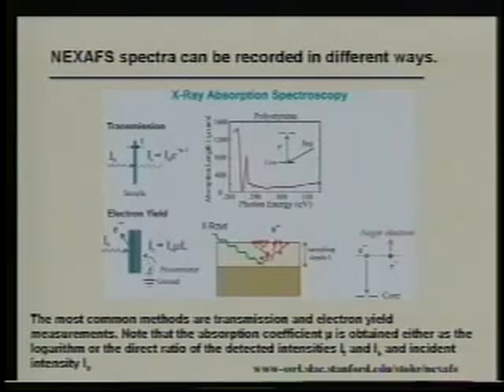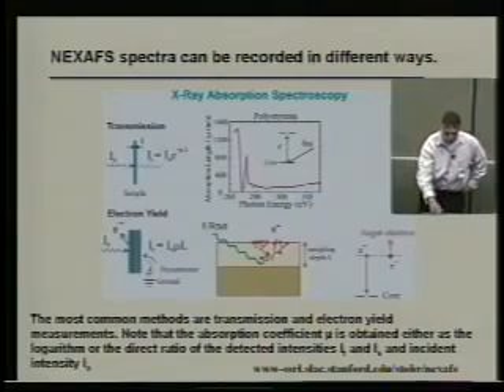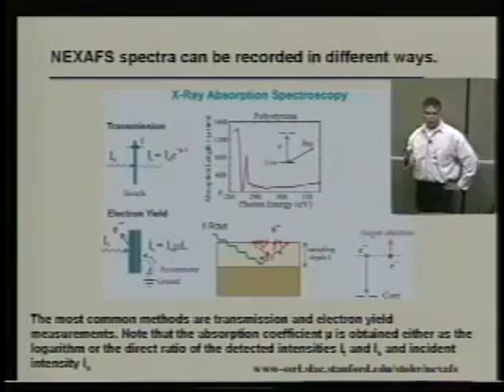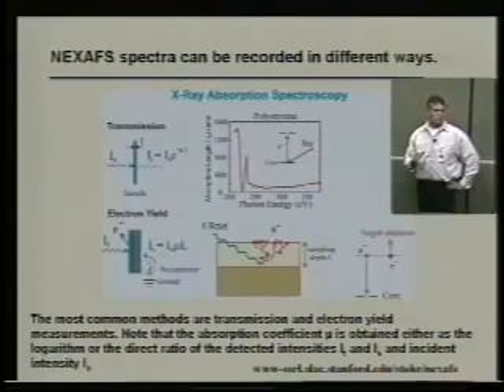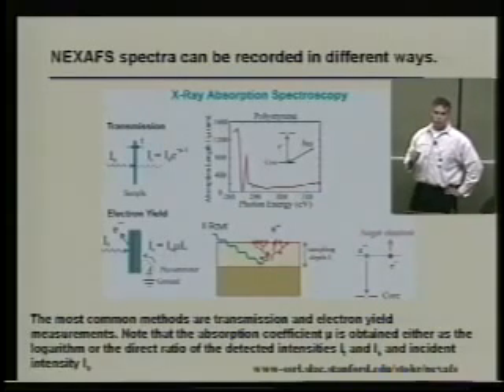So now, how do you record X-ray absorption? There are a number of different modes. The top mode I've shown is transmission. Basically, you shine X-rays on your sample, and the X-rays become attenuated as they go through your sample, and the ratio of your incoming X-rays to your outgoing X-rays is proportional to the exponential of the absorption coefficient times the thickness.